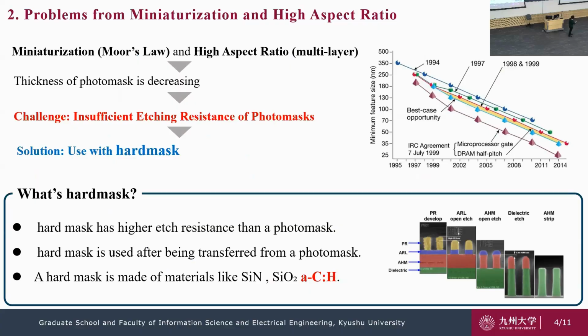There is a problem from miniaturization and the high aspect ratio. The semiconductor device size is getting smaller and smaller by year, with higher aspect ratio. So the thickness of the photomask is decreasing. The problem is the decrease in the etching resistance of the photomask.